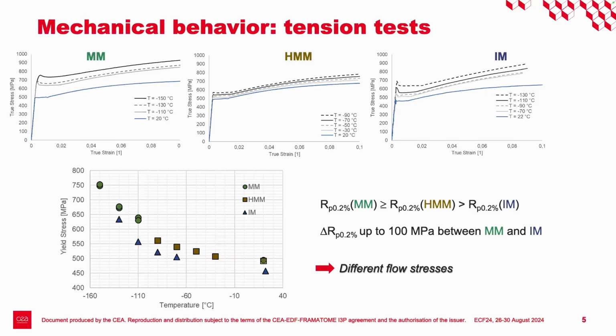So we have performed some experimental characterization of these materials. These tests have been performed at EDF. As you can see, we have tensile results here of the three materials at different temperatures, and we observe the classical evolution of the yield stress versus temperature. The two model materials have more or less the same yield stress, and the industrial material has a slightly lower yield stress.